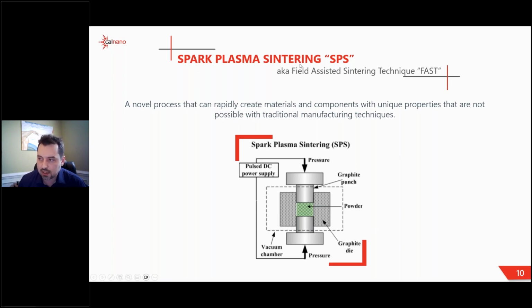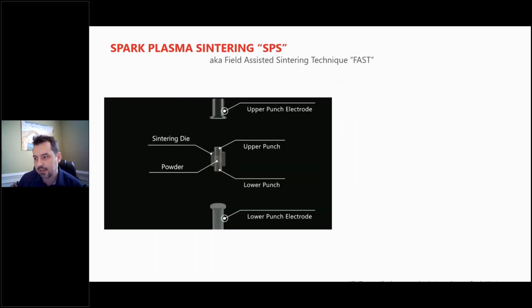And the most important thing to remember about spark plasma sintering is that there's no sparking and there's no plasma. I think early on, the process is done in a vacuum, and many of the original originators of the technology assumed that since we're putting a voltage potential difference in between the material under a vacuum, that's typically a recipe for plasma. However, the voltages are very low, and therefore more studies have been conducted in recent years, and it's pretty unanimous that there is no sparking or plasma. So a more popular and maybe more accurate name is field-assisted sintering technique. And there's probably 3 or 4 other names that different labs and universities have coined for the same exact technology, which is fine for novel paper writing, but is a little bit of an extra challenge for us on the commercial side, as it scatters much of the positive results that have occurred over the last decades.